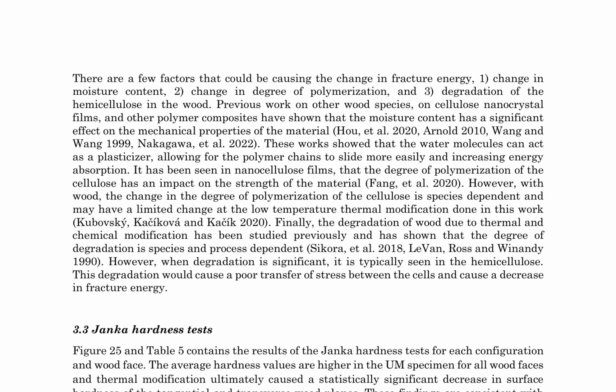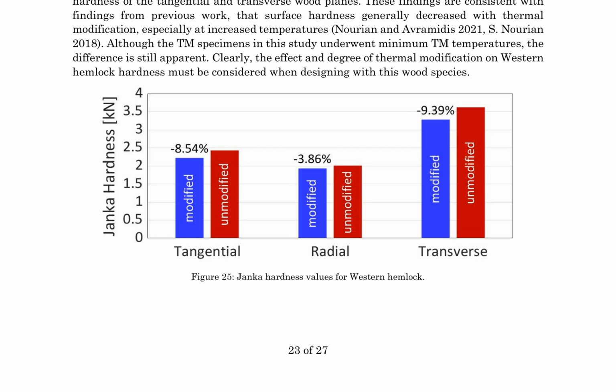The study investigated the impact of thermal modification on the mechanical properties of Western hemlock, focusing on longitudinal and transverse flexure, fracture energy, and hardness. In the longitudinal direction, thermal modification led to a 6.8% increase in modulus of elasticity, (MOE), and a 5.2% increase in modulus of rupture, (MOR). However, in the transverse direction, while MOE increased by 6.7%, the transverse MOR experienced a significant 28% drop. Fracture energy for both radial-longitudinal (RL) and tangential-longitudinal (TL) systems showed a substantial reduction due to thermal modification. For the RL system, initial and total fracture energies decreased by 41% and 47%, respectively.